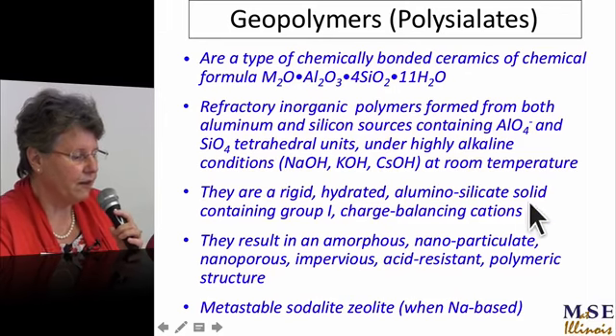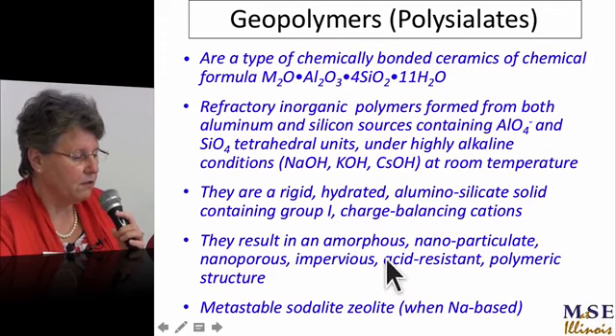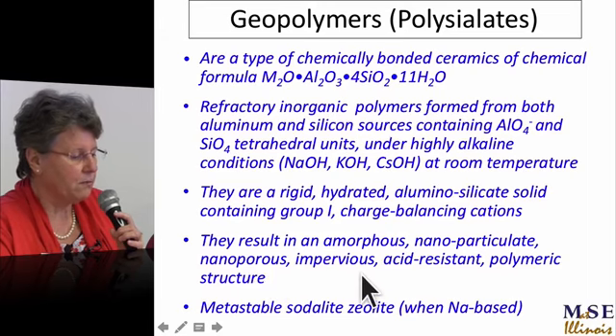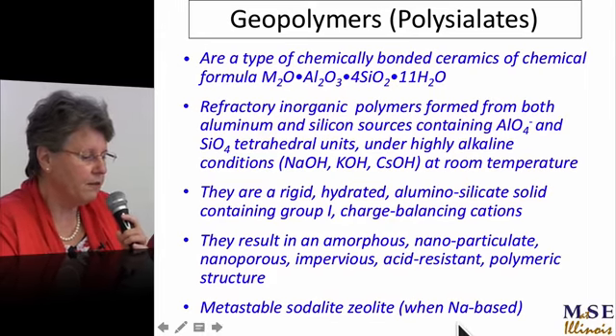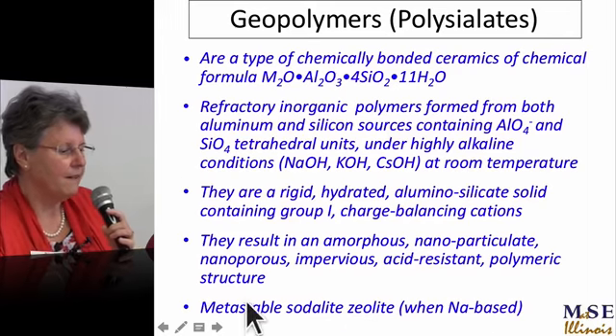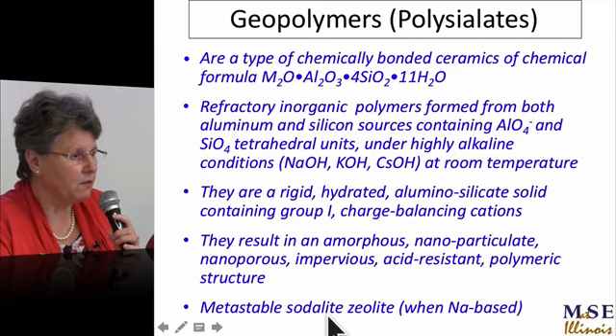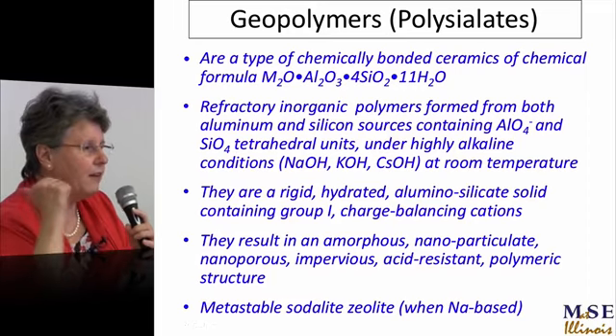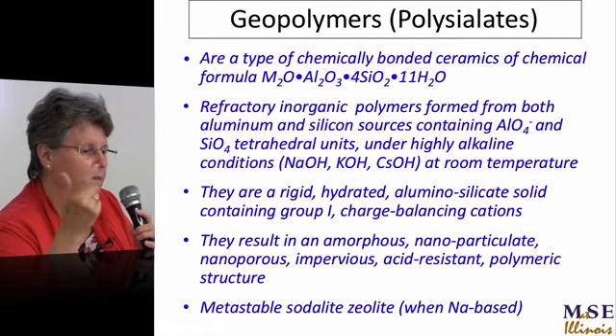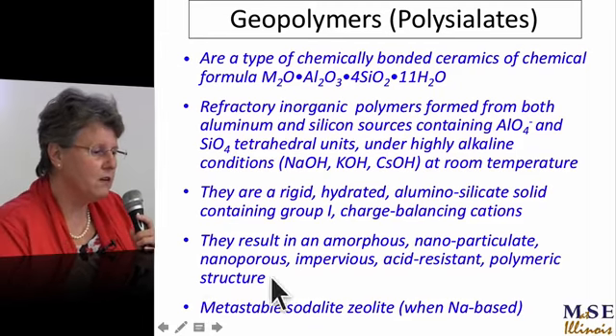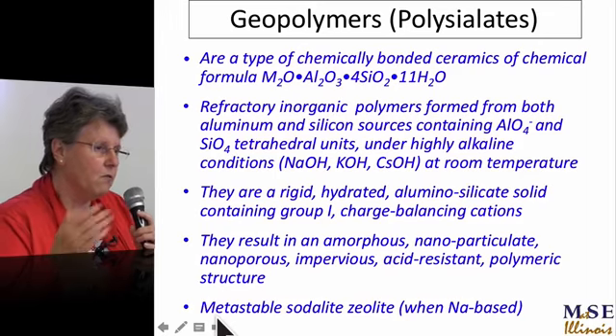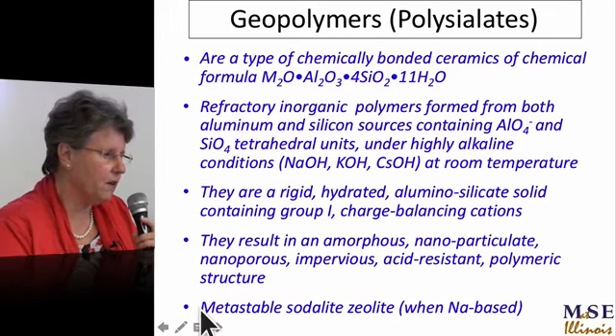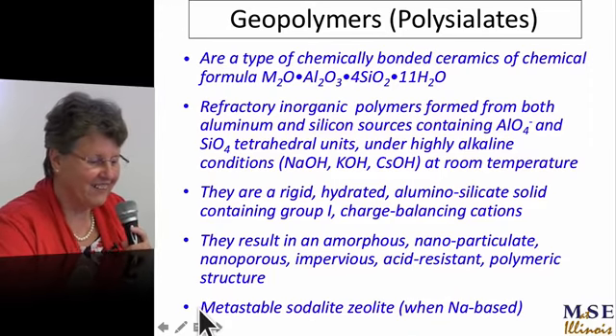They are a rigid, hydrated aluminosilicate solid containing group 1 charge balancing cations. They result in an amorphous, nanoparticulate, nanoporous, impervious, acid-resistant polymeric structure. And there's metastable zeolites. In the case of sodium-based geopolymer, it's a metastable zeolite, or maybe sodalite. I learnt a lot of my stuff from Ken MacKenzie in New Zealand, and we sort of cross-fertilised each other, and then I'm getting more and more knowledge by hanging around with Joseph and his team.